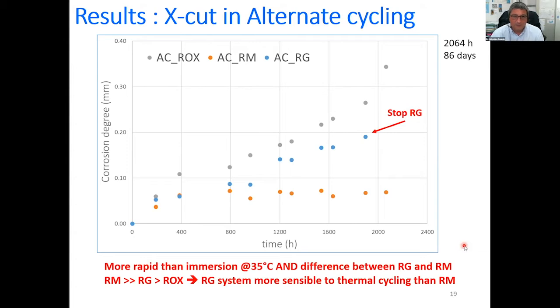Now the results for the X-cut panels in the alternate cycling. Again, this is a test that is more rapid than the immersion at 35 degrees C. We find again that the ROX system shows the highest corrosion degree values. But now it is possible to see a difference between the RG and RM systems. In fact, we had to stop the test for the RG panels because we observed some delamination of the coatings quite rapidly. So again, it seems that RG is more sensitive to thermal cycling than the RM system.